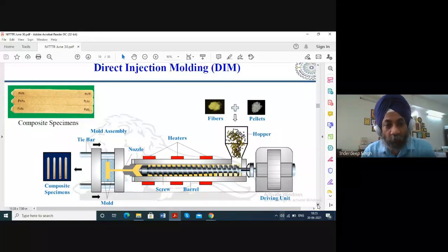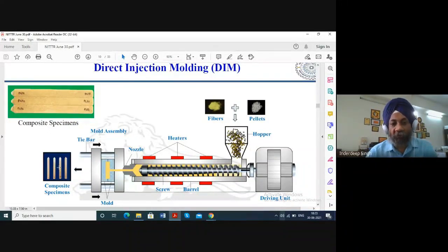These are the composite parts that you see on your screen. It is a direct injection molding part which has been fabricated using natural fibers. On your screen you can see the natural fibers and pellets. We combine these fibers and pellets and make a batch, and then we feed that batch into the hopper of the injection molding machine, and we can get the composite samples here.